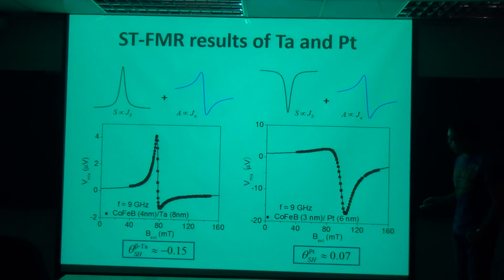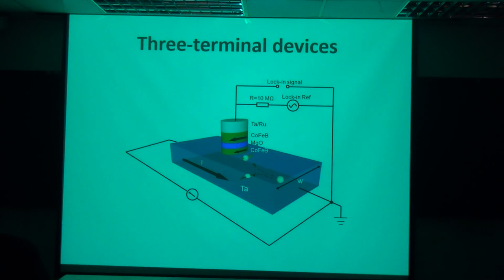So in the past, actually at the beginning, a lot of people who work in the field of spin Hall effect or spintronics focused on platinum. But later we found that, at least using spin torque FMR, it seems that for tantalum, or at least in the high resistivity state of beta tantalum, it has a spin Hall angle with a magnitude almost twice as large as this one. So at that time we thought, maybe we should use this to really demonstrate spin torque switching.